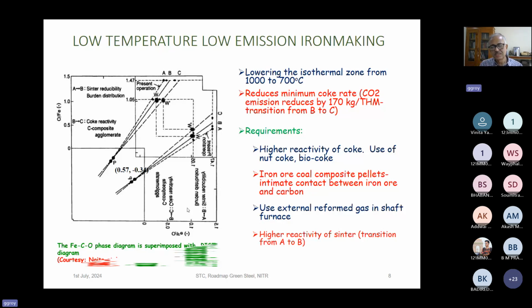So at 1000 or 900 degrees centigrade, around 70% CO should be kept in the equilibrium for the Wustite-Fe equilibrium. And only if you supply CO above that value, that is above 70%, can you convert the FeO to Fe. So 1 mole of FeO will be converted to Fe when you supply CO in excess of 70% in the CO-CO2 mixture. And it increases further with increase in temperature because of the nature of the curve. At higher temperature, the equilibrium CO requirement increases. And even at 900 to 1000 degrees centigrade, it is around 70%.